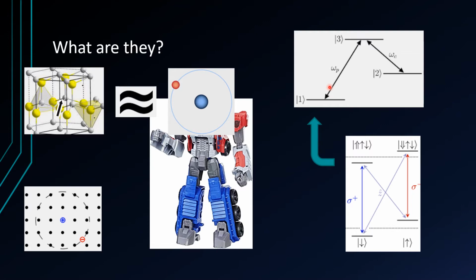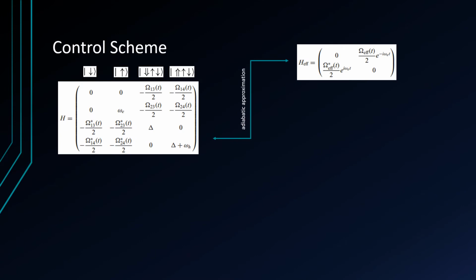Since the selectivity of the excitation depends on strong splitting between the 1 and 2 states, there is a lower bound of about 2.25 Tesla of magnetic field for this pumping scheme to work, and it really should be even higher for practical purposes. However, there is a conflict, namely that large magnetic fields harm T1, and even worse, actually leave us unable to perform traditional microwave control of the spin qubit. Instead, zinc oxide donor spins are coherently controlled with a different scheme based on the detuning of the applied pulse from the qubit to the exciton transitions, giving us an equivalent degree of control.